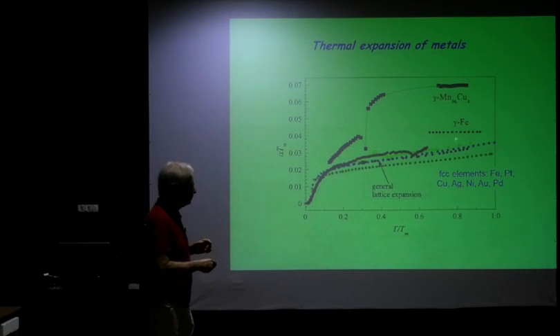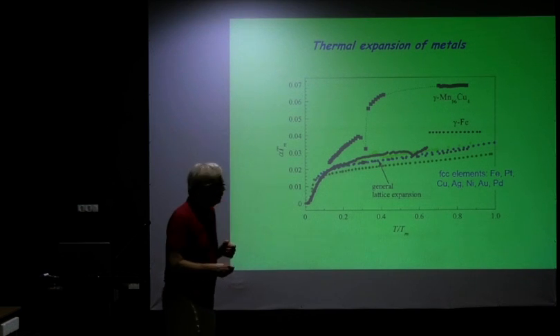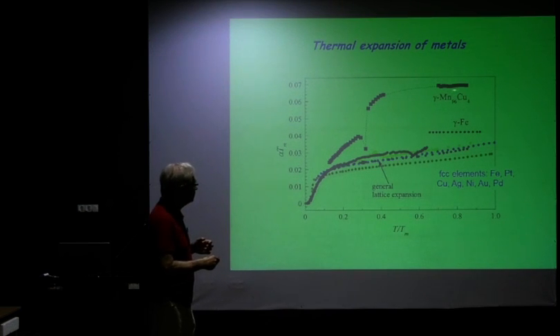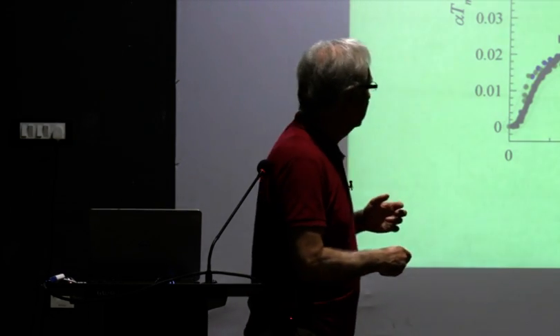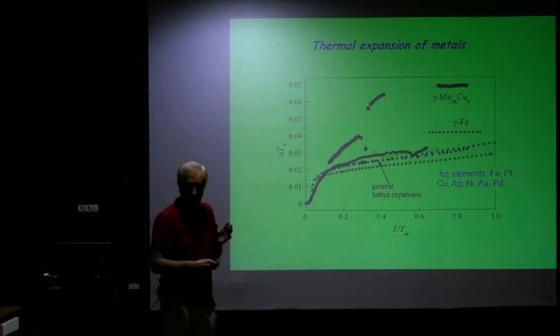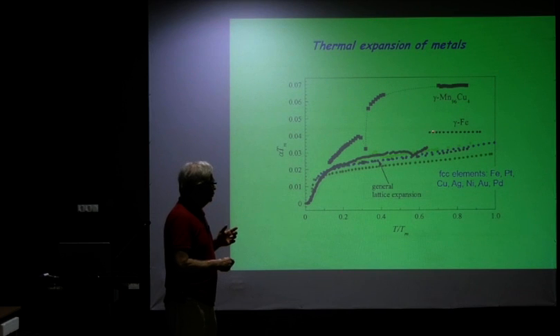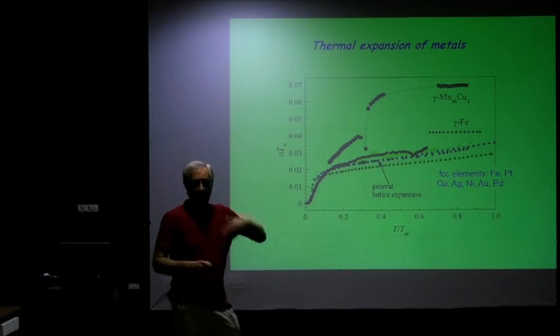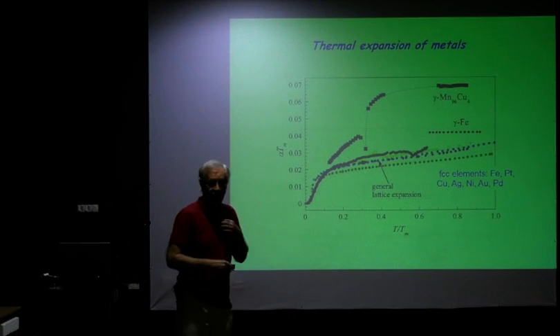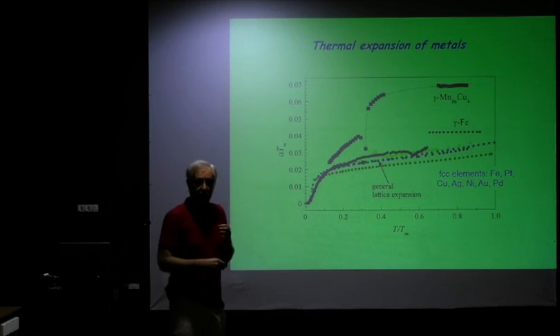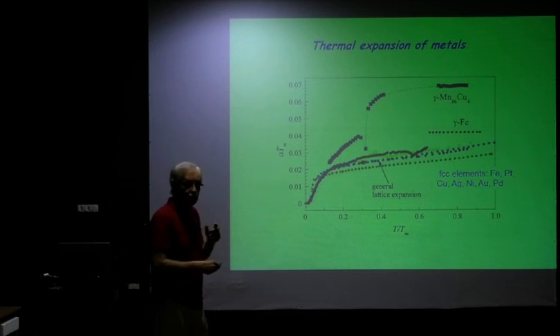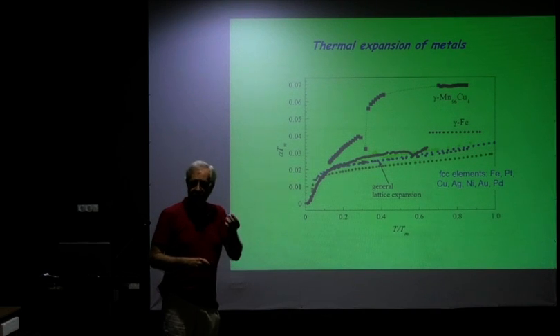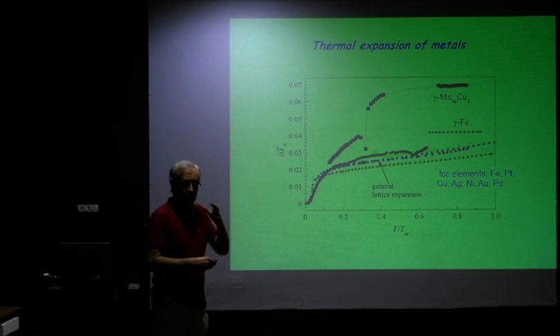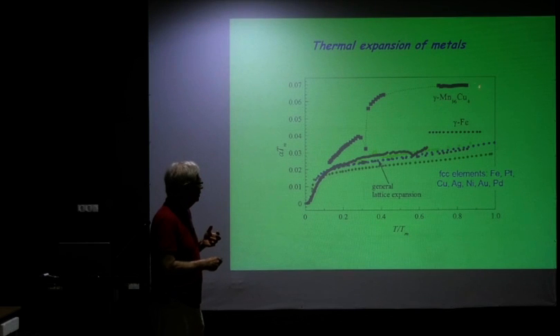But when you look at gamma iron, FCC iron, and when you look at gamma manganese, that's FCC manganese, these are tremendously anomalous, okay? You can measure the thermal expansion coefficient of gamma iron at high temperatures. You get practically no variation and a very high value. You can also go to 1400 Kelvin where gamma manganese is stable, and by some high-temperature X-ray measurements, you can also make a measurement over there.